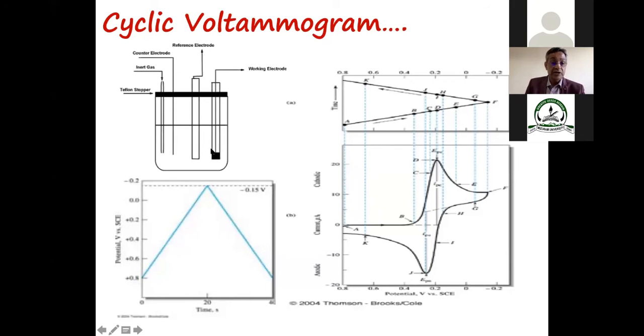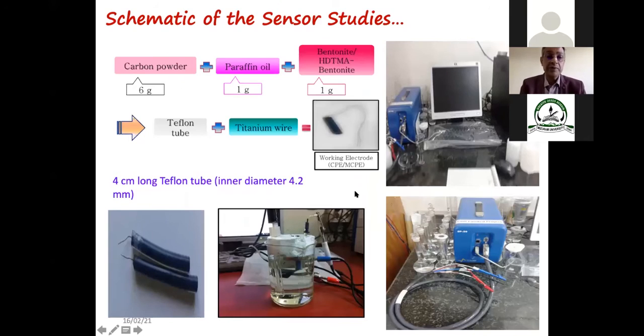This working electrode we used to fabricate. How did we fabricate it? We have fabricated it using our own materials, okay. This is the paraffin oil by which we are making the paste, and carbon powder that we have used. Carbon powder, naturally, we can develop in the lab itself, or you can purchase it. So the carbon powder that we have taken along with the paraffin oil and our material, we have made a good paste, and this paste has been filled in this, okay.